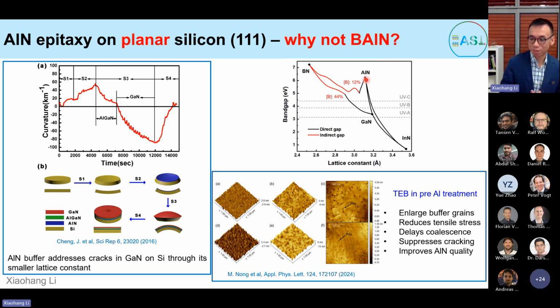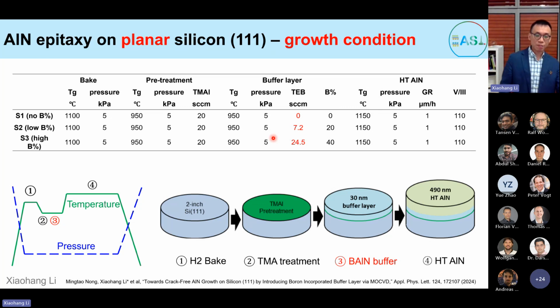However, because we have worked on the boron nitride system for a long time, we were thinking, why don't we just use boron aluminum nitride or boron gallium nitride, because those materials can create the kind of smaller lattice you need to provide compressive strain for silicon, right? That's number one. Number two is that boron aluminum nitride tends to have more columnar growth, right? Which means that you can actually enlarge the buffer grains. That buffer grain will delay the coalescence, which in turn also suppresses or mitigates the accumulation of the tensile strain as well, right? So you kind of hit two birds with one stone, and then we can potentially realize crack-free aluminum nitride on silicon 111.